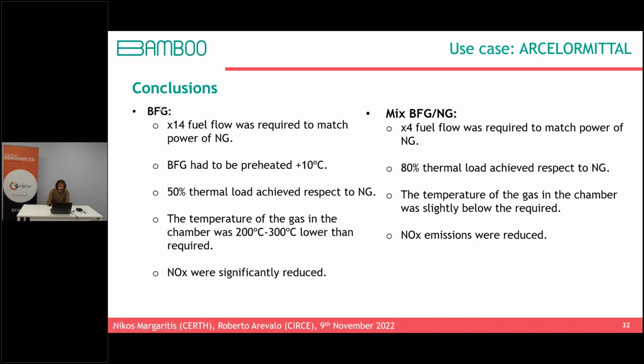comparing the experiments and simulations carried out with BFG, meaning only BFG as fuel and the mix of BFG and natural gas, we can see that, of course, when we use only BFG, we need much higher flow of gas because of the low heating value. Okay, this is pertaining to the question. BFG had to be preheated by 10 degrees Celsius. So, okay, it's not a huge pretreatment, just a small one.